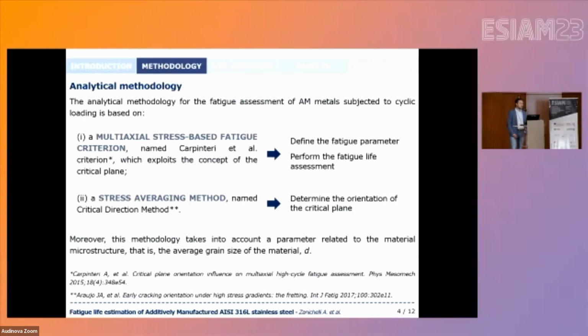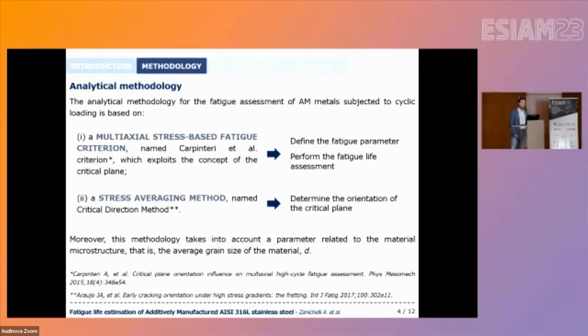Let me firstly describe this methodology, which is based on the joint application of a multi-axial stress-based fatigue criterion, exploiting the concept of the critical plane, that is the Carpinteri criterion, and a stress averaging method, that is a critical direction method. In particular, the Carpinteri criterion is used to define the fatigue parameter as well as to perform the fatigue life assessment of the component, whereas the critical direction method is employed for the determination of the critical plane orientation.